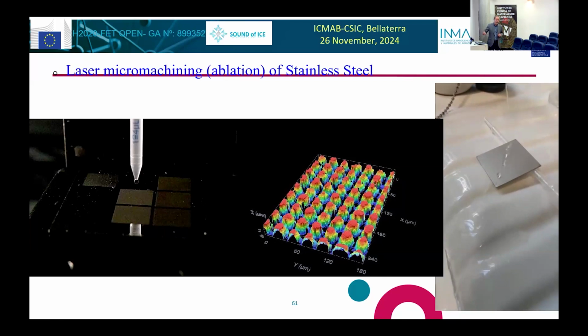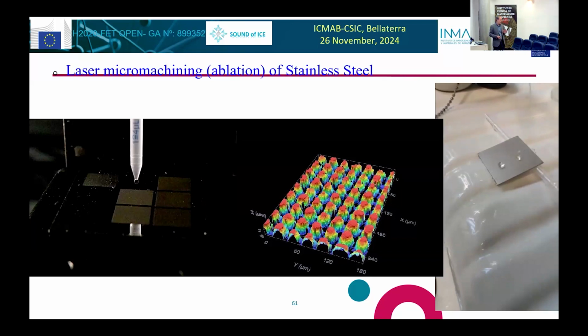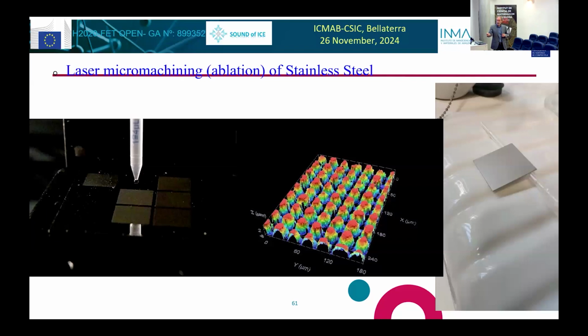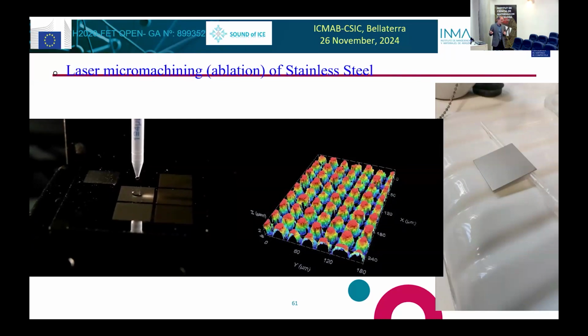And you can see this is stainless steel. It took us 3 years to do this without causing an accelerated corrosion of the stainless steel. So it maintains the properties of the stainless steel. You can see that the wetting angle is very high. It's super hydrophobic, as is this one on this side that you will see here. So this is stainless steel.